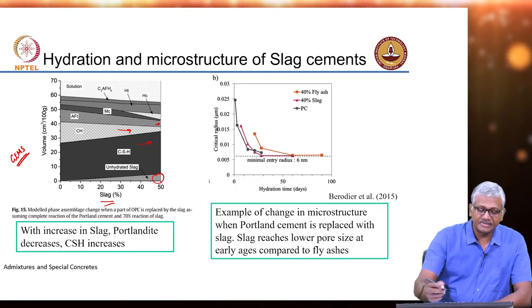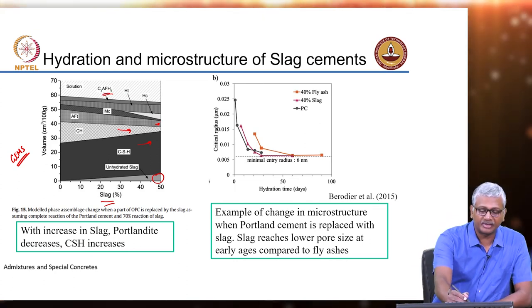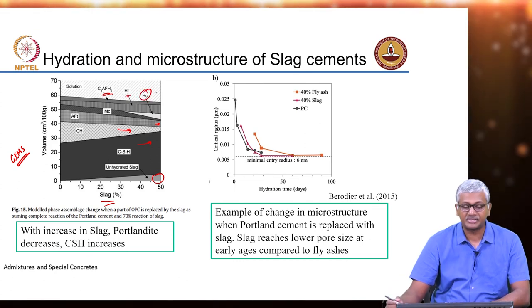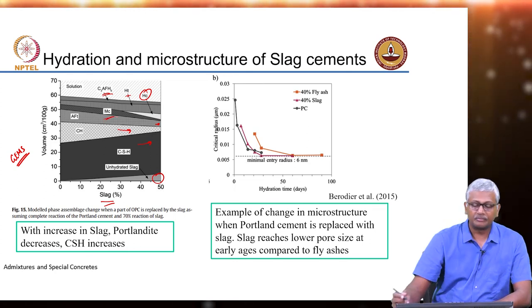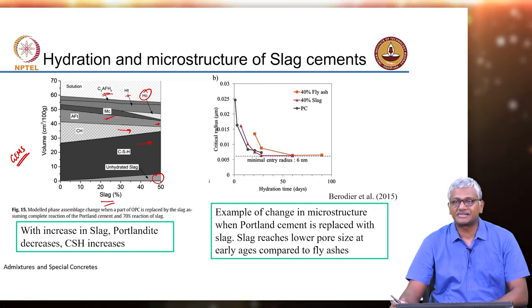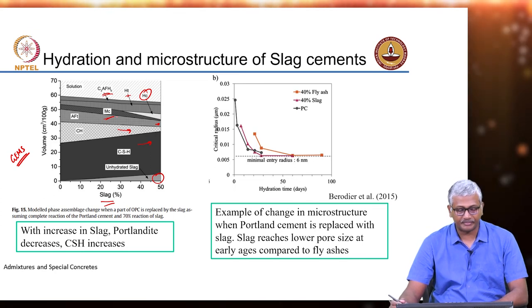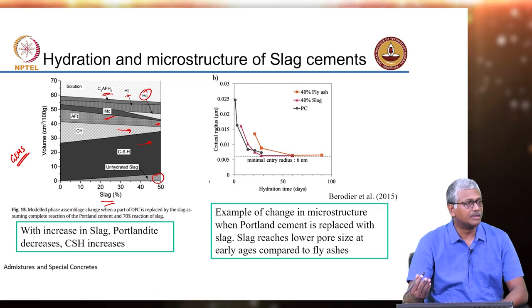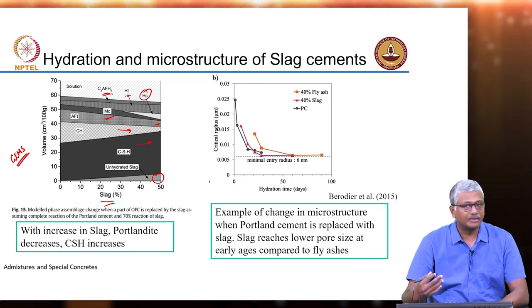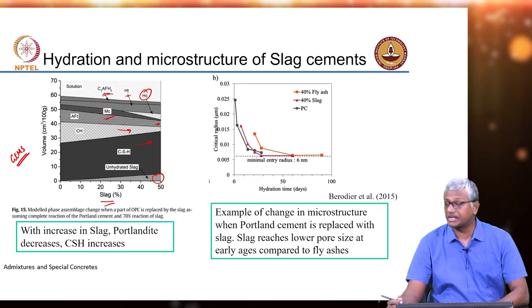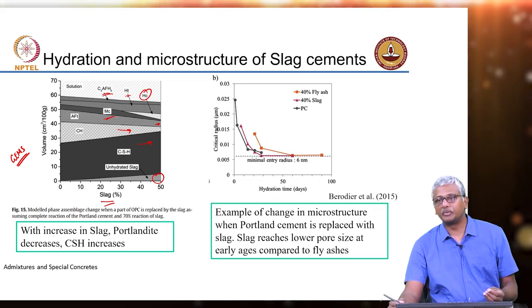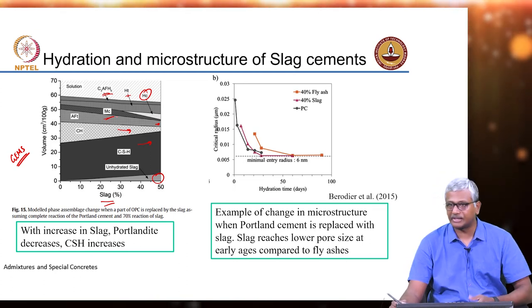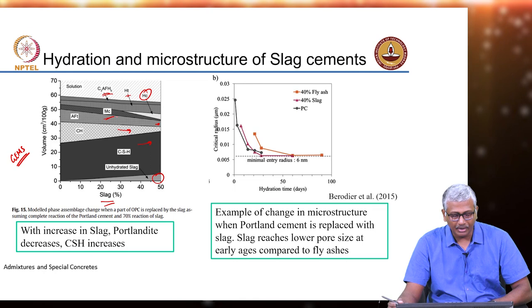There are other phases that could also form in the system — calcium aluminoferrite hydrates, hydrotalcite, hemicarbonate or monocarbonate could form in some instances, provided there is some calcite or calcium carbonate available in the system. Because there is alumina from your slag, and carbonate from your calcite or limestone, they can combine to form carboaluminates — just as we discussed earlier, carboaluminates form when you have alumina and calcium carbonate in the presence of portlandite.